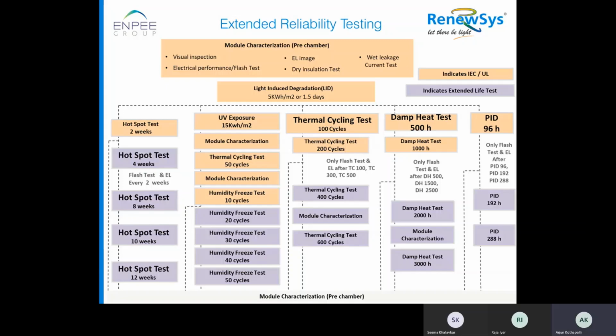Then the modules are divided into four lots. The first lot will go for hotspot testing under natural sunlight. It stays for 2 weeks. Once it completes 2 weeks, we do EL and flash test to ensure what the power drop is, and we extend this hotspot test up to 12 weeks. For every 2 weeks, we recheck the EL and flash again.